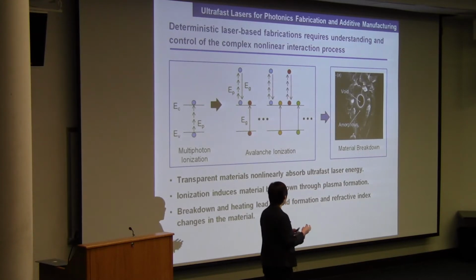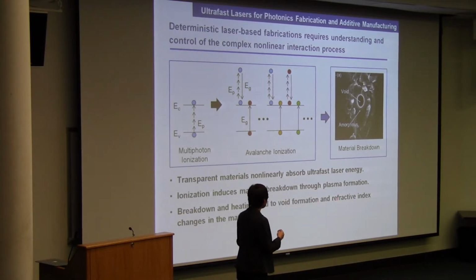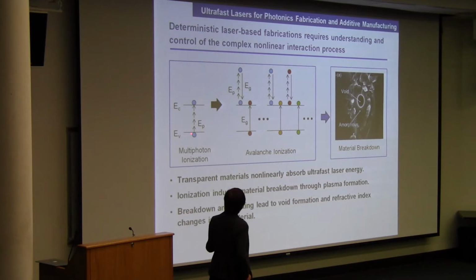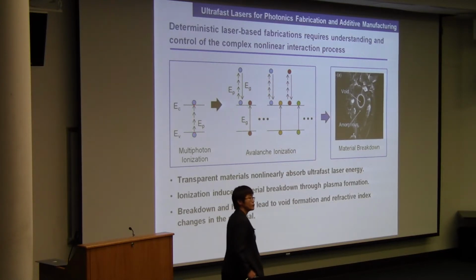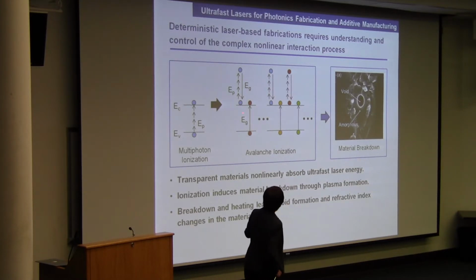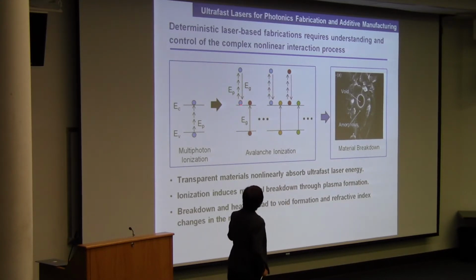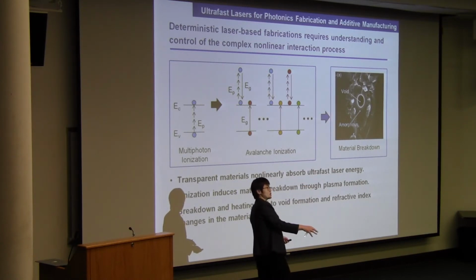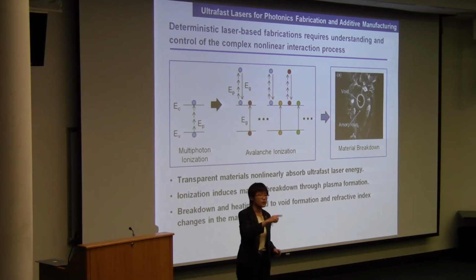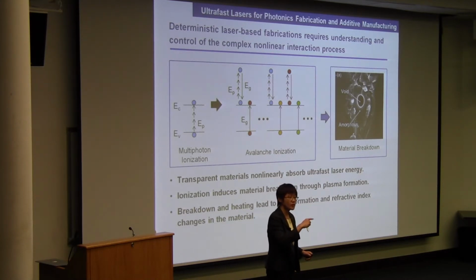But for ultrafast laser, such as refractive index modulation to write waveguides, or for welding, it starts with multi-photon ionization. When the electron receives enough energy, it goes from the valence band to the conduction band, so you generate free electrons from the photons of the ultrafast laser. Once the electron gets to the conduction band, it continues to receive photon energy. Once it receives photon energy exceeding the band gap, it generates another electron, and that electron drops to the valence band to cause more ionization. This whole process iterates, and you get avalanche ionization.